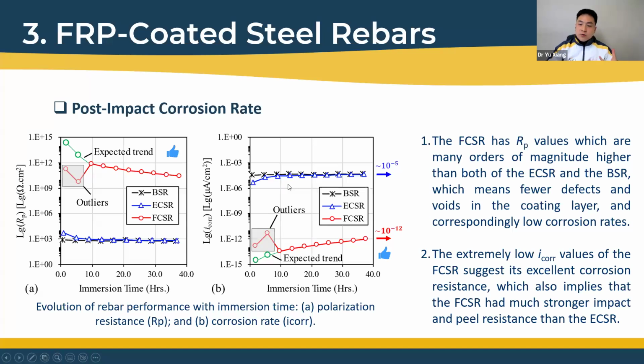This in turn proves that the FRP coated steel rebar has much stronger impact and peel resistance than epoxy coated steel rebar, because the mechanism is easy to understand: the fibers inside the coating layer can serve as a reinforcement of the coating. So normally we can think the FRP coated steel rebar is an upgraded or strengthened version of epoxy coated steel rebar.